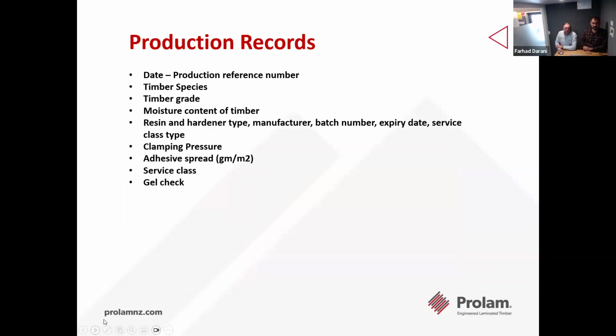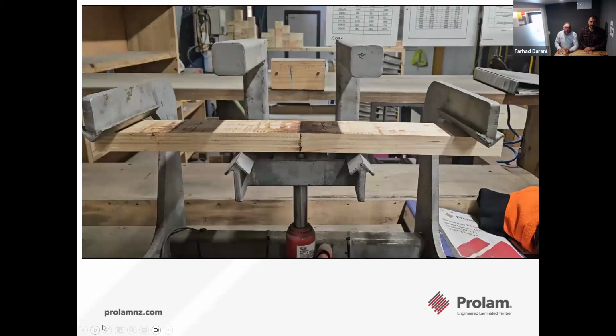This is a bit of our production record. These are the records we keep every day for our quality control: date, species, grade, moisture content, the resin type and hardener, the manufacturer of the glue, the batch number, expiry date, the service class type, clamping pressure on the finger joiner, adhesive spread in grams per square meter, and then a gel check. We use a 2-pot glue, so we do a gel check on the glue every day to make sure the batch is going off.